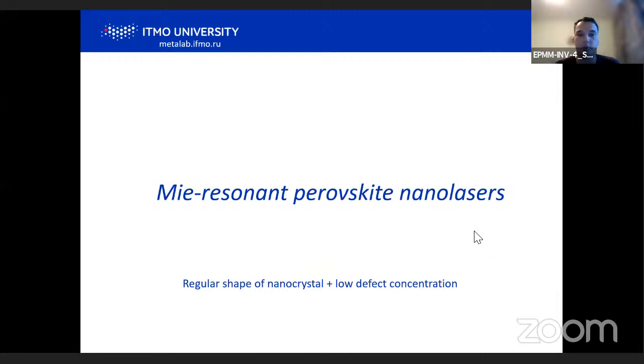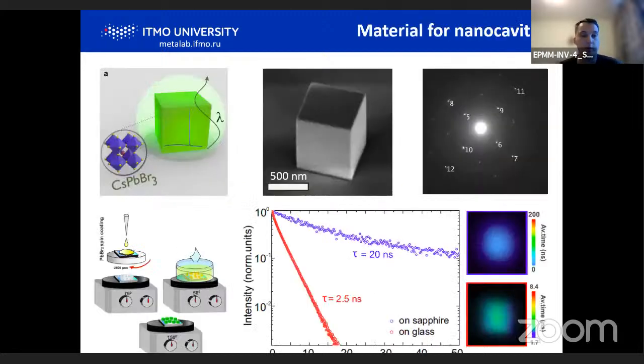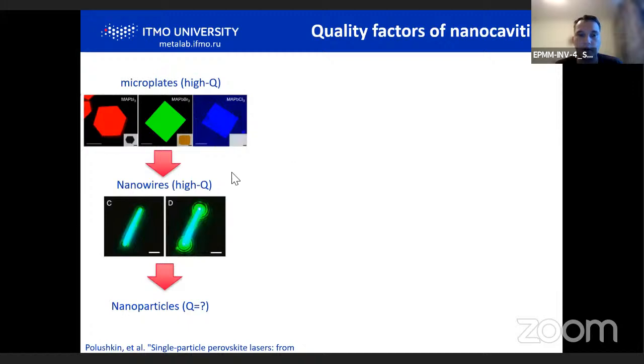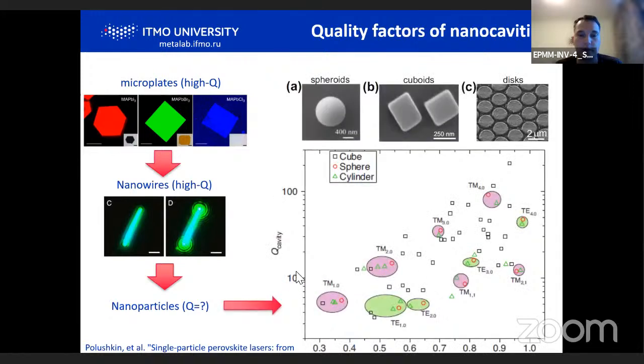And then I switch to my presentation, how we can apply this resonant nanophotonics for nanolasers, because nanolasers is one of the brightest applications in nanophotonics. So we employ a material like cesium lead bromide, which provides us very nicely shaped submicron nanoparticles. And we grow them on sapphire substrate, which is important because we have to provide as high as possible quality of the crystal. And the question is what the quality factor of nanocavities for lasing is, because previously perovskites were used for lasing in the form of microplates or nanowires, but with microscale lengths. But if we use completely sub-wavelength nanoparticles, what Q factors can we expect for these designs?